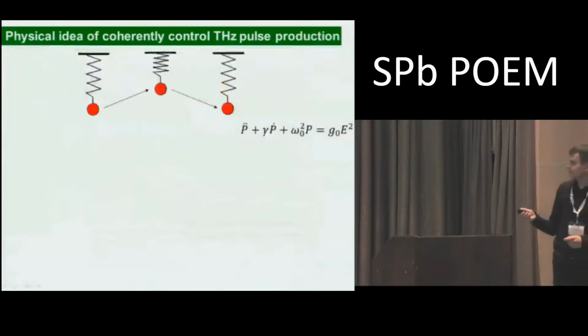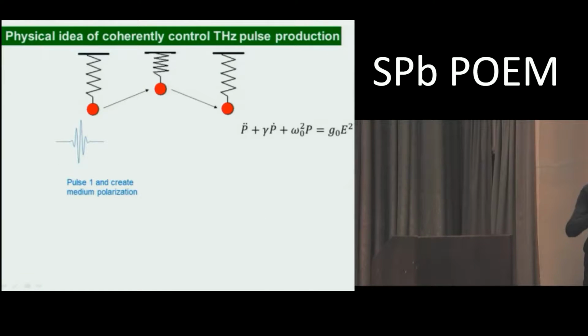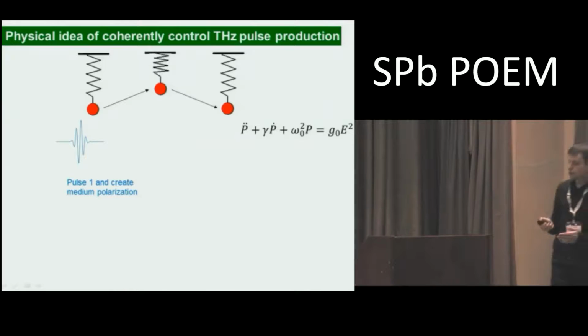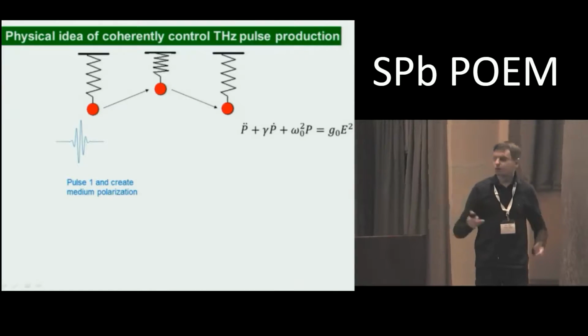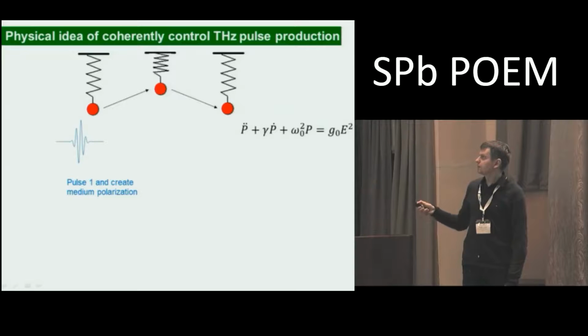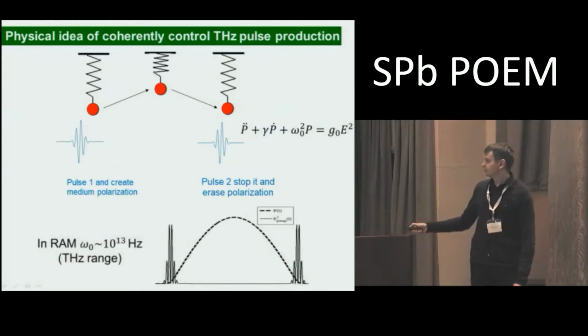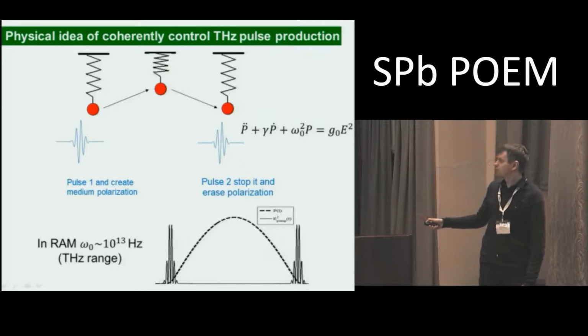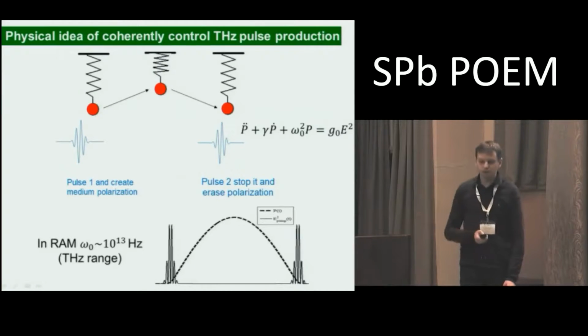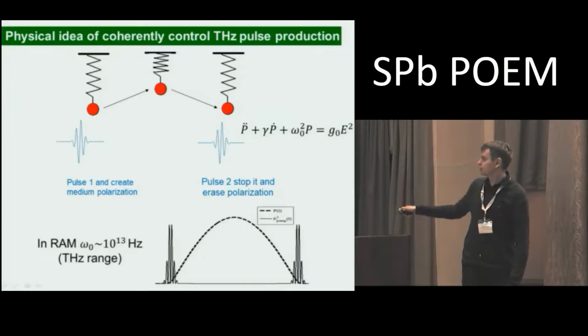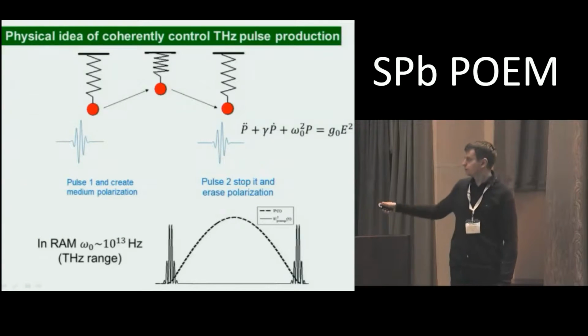Yes, thank you. The second method, which was proposed by us recently, is the generation of a single cycle pulse when the medium is illuminated by a femtosecond pulse train. The basic idea of this method is illustrated here. We have a nonlinear medium with nonlinear oscillators, and the polarization is proportional to the square of the electric field, which is typical for a Raman active medium. The first pump pulse creates the medium polarization, and the second pump pulse, if it arrives at a distance of half a period of the medium proper oscillator, stops this polarization. As a result, the polarization of the medium is just a half wave of medium displacement.